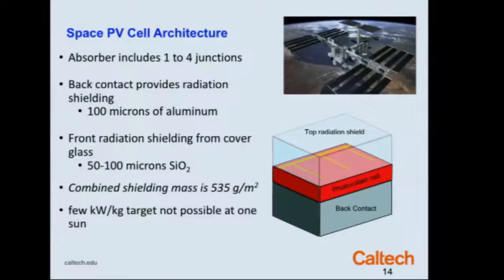So the most common design for these kinds of power systems, like the one on the International Space Station, all feature this design, where there's a photovoltaic cell. There's a very thick layer of glass. I showed you techniques on Tuesday for making extremely thin, lightweight solar cells. But the problem is I can make the solar cell as light as I want, and I still have to put 50 to 100 microns of glass in front of this solar cell. And I've lost all the weight advantage I had from making the solar cell thin.